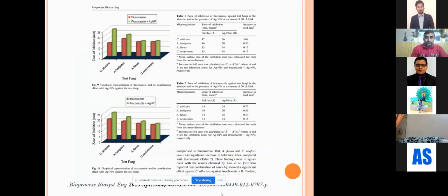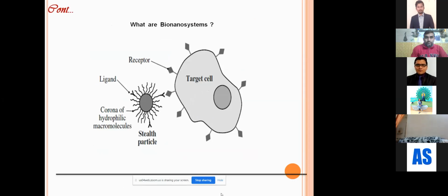This was one of my papers which has found the most citations, where we worked with silver nanoparticle with fluconazole and itraconazole, and we saw the activity with the fungi, how they are able to control it when we incorporated silver nanoparticle along with the common antibiotic which was being utilized for the control of fungi. So now I'm going directly into the work that we have done.